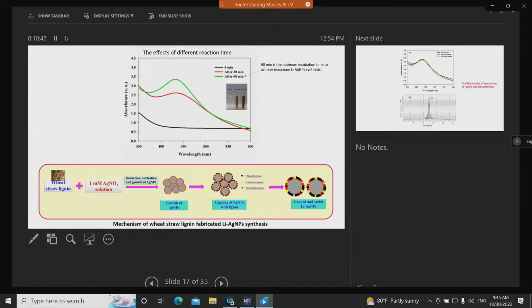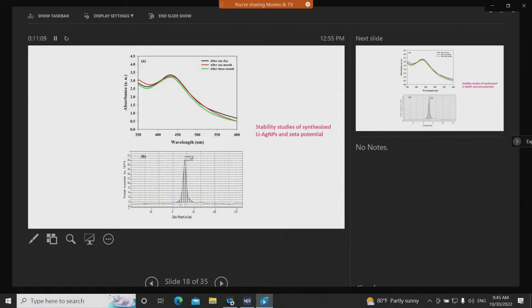And this is the probable mechanism of wheat straw lignin-fabricated lignin silver nanoparticle synthesis. It shows mainly the phenolic, hydroxyl, and carboxyl groups capped on the surface of the silver nanoparticles. So stable and capped lignin silver nanoparticles were synthesized using the wheat straw lignin.